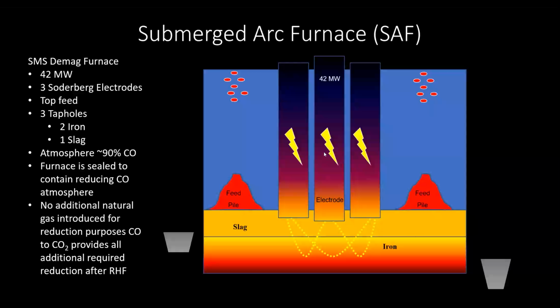You add basically graphite pellets or carbon pellets at the top, and they graphitize in place. You feed down into there. It's a top feed system. Our atmosphere in the furnace is 90% CO, so that CO going to CO2 helps drive further reduction of the FeO in here.